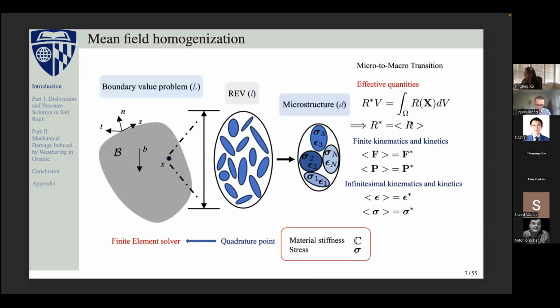And also, if we consider small strain, we can of course take the strain and the Cauchy stress. With that understanding, we can pass the stiffness tensor and stress into the integration point, into the REV behavior, and we use that behavior to do the finite element simulation. So this definitely couldn't capture as many details as what I just introduced in the full field homogenization. But on the other hand, it's not that time consuming because it has the analytical solution. We can capture some information of the microstructure, and we can save some computational time. So that is the main focus in this study.